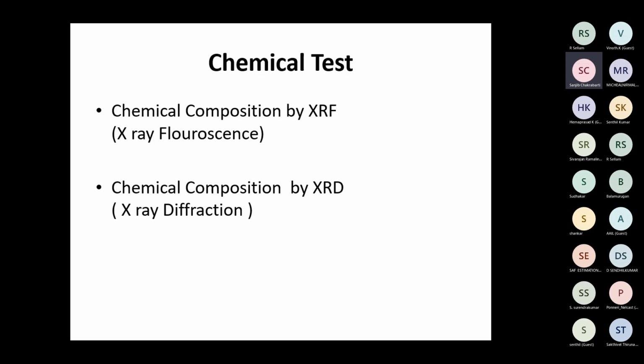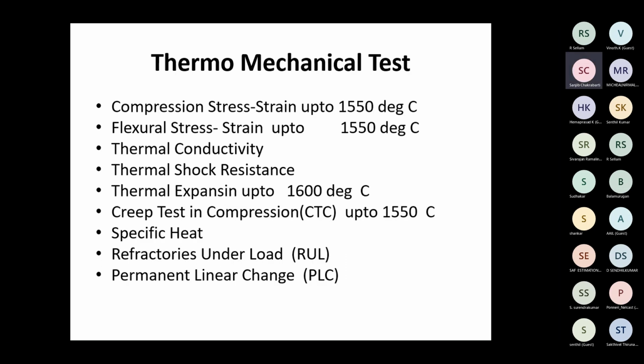Now the thermomechanical test. Thermomechanical is very important. Why thermo? Because you do the mechanical test under temperature. You have to test it mechanically under temperature. Compression test up to 1500 degrees centigrade, because inside the furnace it is always under heat. So you have to test it not at ambient or room temperature.